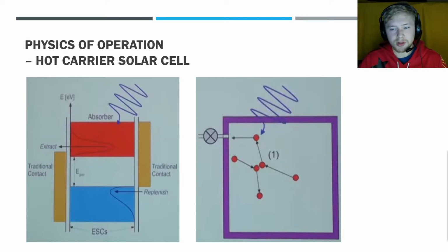But if these particles are able to scatter with the walls of the container in our tank, then this can potentially lead to some kind of energy transfer to the material that is holding the charge carriers, in this case, the semiconducting material, which is acting as the absorber. This can lead to thermalization loss, and ideally we would like to reabsorb this energy at some later scattering event. To insulate our tank against this thermalization loss, we need large phonon band gaps in the absorber material, so these phonons, which are created during scattering events, are long-lived. This causes the phonon population to stay hot.